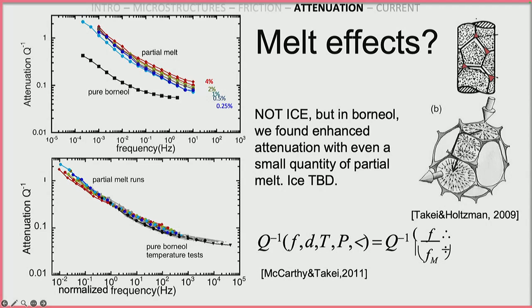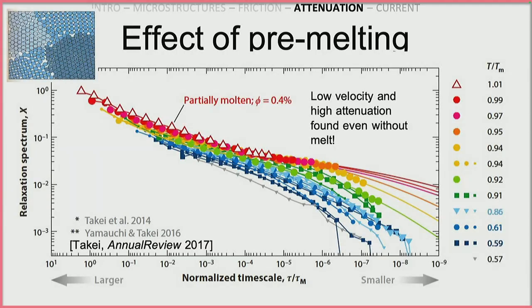However, after I left in 2011, they realized that comparing our melt samples with this pure Borneol, which was actually measured at 60% of melting, is kind of not a fair comparison. What happens as you approach melting? Well, I'm going to present this effect called pre-melting.